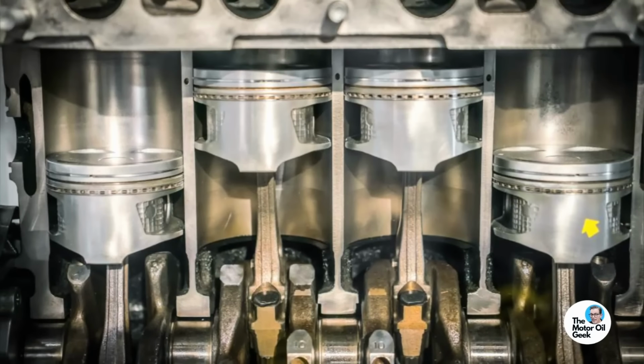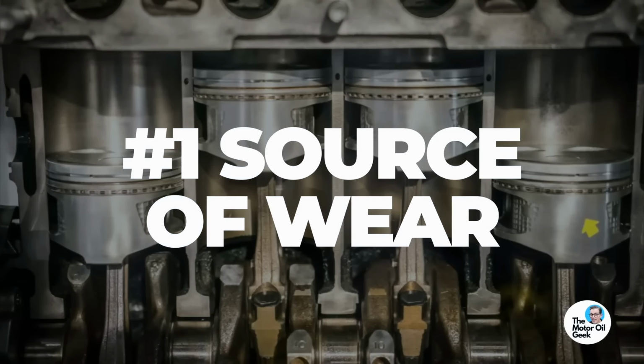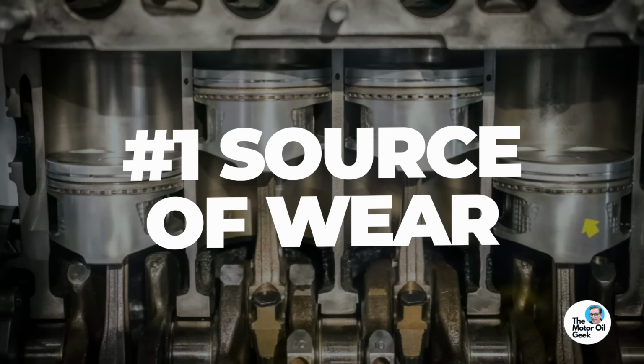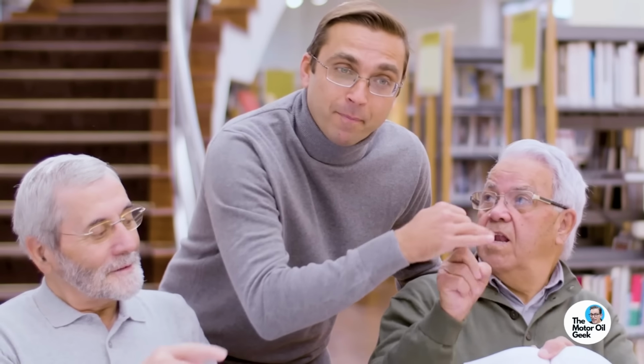Then I finally remembered, oh, this is why the wear is lower than we've seen in the past with the same engine setup. The reason why is that the piston ring rubbing against the cylinder wall is the number one source of wear in the engine. So by changing the coating and changing the way we hone the engine, we greatly reduced how much wear occurred in the engine, which is why these numbers are so much less. So when you see a few more of these numbers in a minute, some people are going to say, wait, those numbers are way too small. You can't even read that.